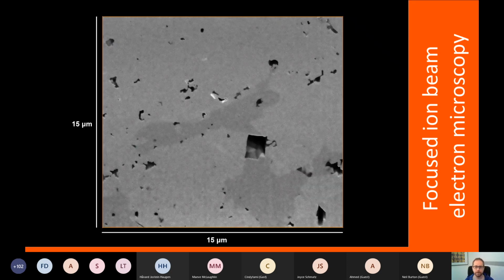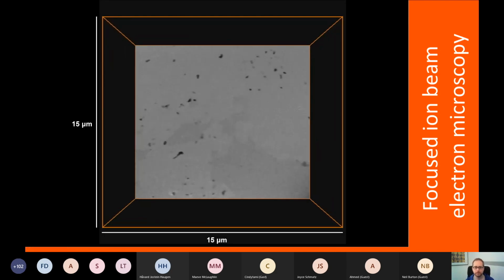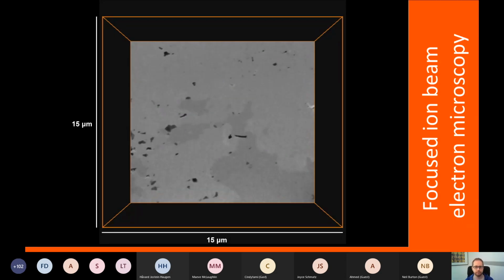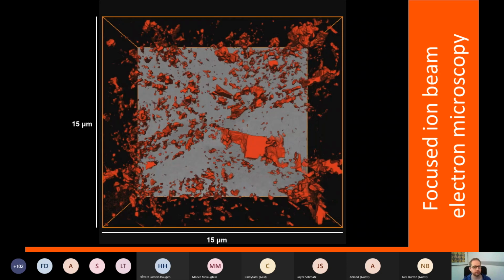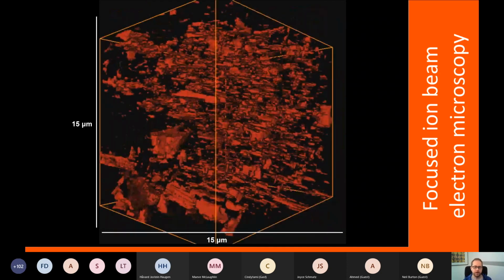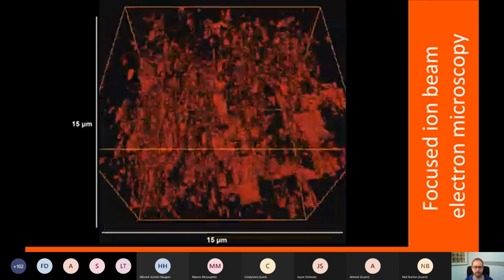So the disadvantage is, compared to X-ray tomography, which we will learn about tomorrow much more, is that FIB tomography is destructive, but it allows us to image at very high resolutions with the electron beam down to nanometer scale. So what you see here is a video of a feldspar that has porosity inside. You see all these blacks here is porosity. This is actually a backscattered electron image. You see there are at least two types of phases here, the darker contrast one and the lighter contrast one. This is about 15 by 15 micrometers. And now you see this sequential slicing and imaging throughout the material, very similar to X-ray tomography if you have looked at that before. And now we can reconstruct this pore space or any area of interest in 3 dimensions to analyze this at very high resolution.